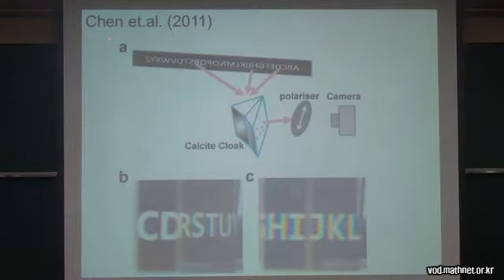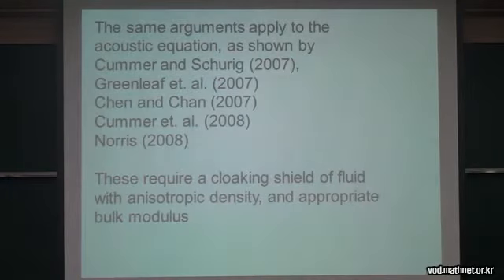And a similar experiment by Chen et al. in 2011 was based on the same idea. And here they demonstrated the letters of the alphabet would be jumbled up if the cloak was absent, but in the right order if the cloak was present. And actually the same arguments apply to the acoustic equation, as shown by Cummer and Schurig, Greenleaf et al., Chen and Chan, Cummer et al., and Norris in 2008. And these require a cloaking shield of fluid with anisotropic density and appropriate bulk modulus. So materials with anisotropic density have application to cloaking, actually.